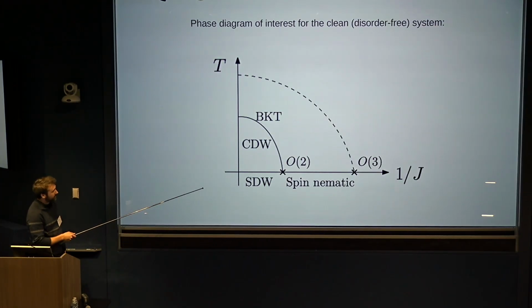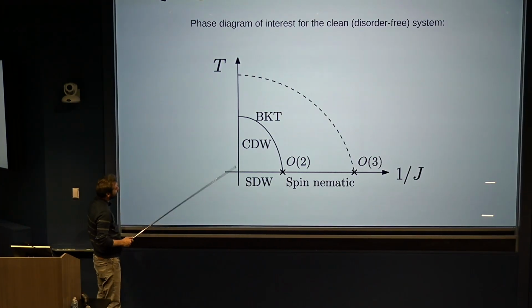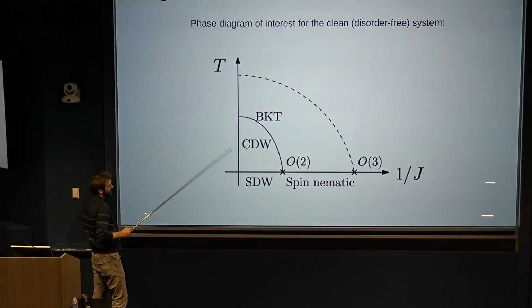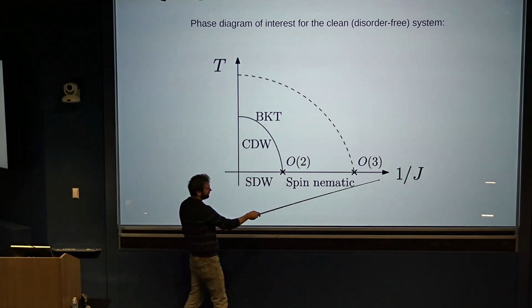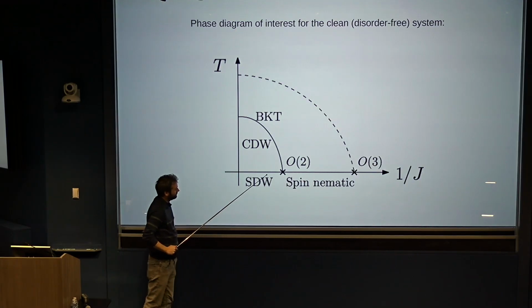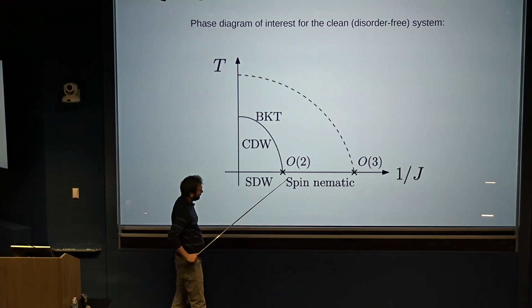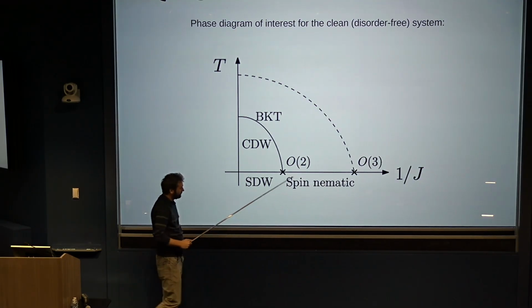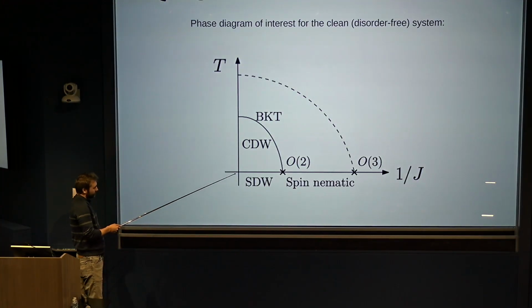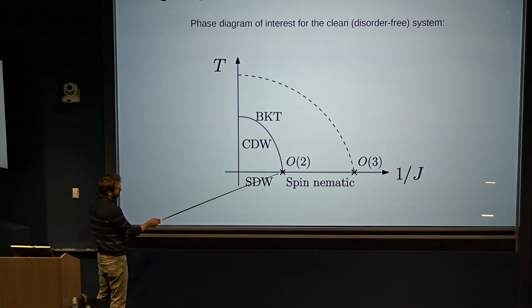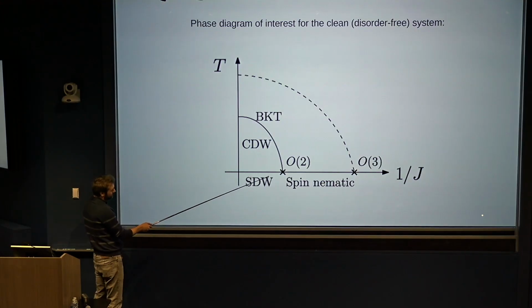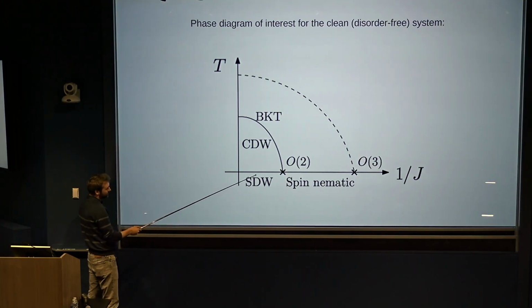And this realizes this phase diagram. So the y-axis is the temperature, and the x-axis is 1 over the stiffness. So going to the right is actually lowering the stiffness for order parameter fluctuations. And so focusing first on zero temperature, at large stiffness, we start in the spin density wave state, or equivalently, this is the spin stripe.